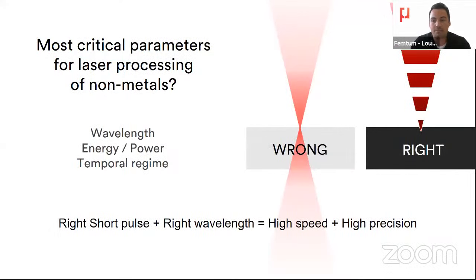And you have 3 main parameters that you can play with a laser. Basically, you have to have the right wavelength, energy, power, and temporal regime of your laser. And this is a big claim, but basically what you need is the right short pulses at the right wavelength if you want to have high speed and high precision processes. And why do you need the right short pulses? Basically, in the worst case, you have CW laser, in which you melt the material. And the goal here with short pulses is to vaporize the material and not induce thermal effects.